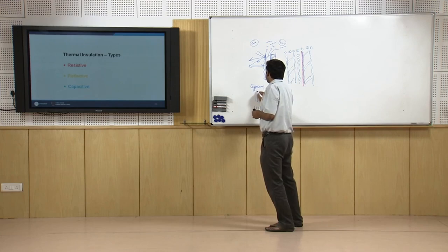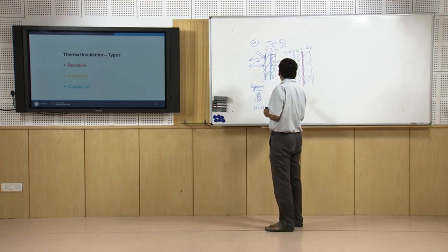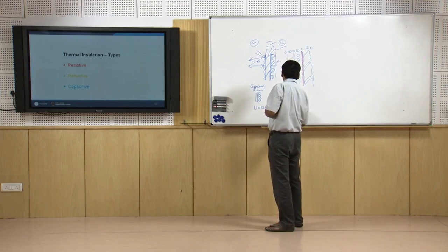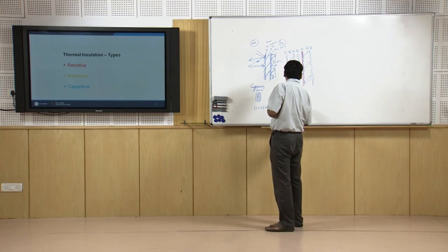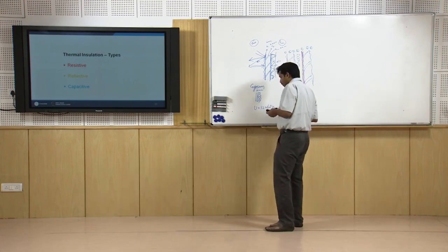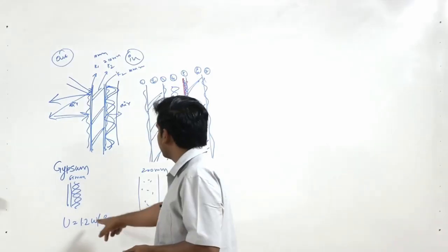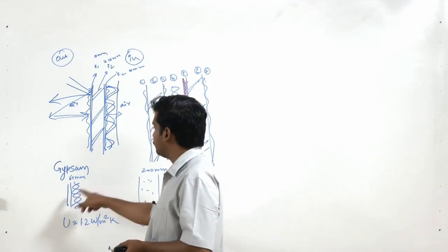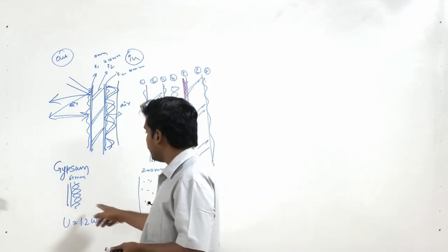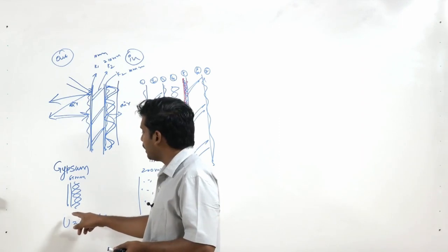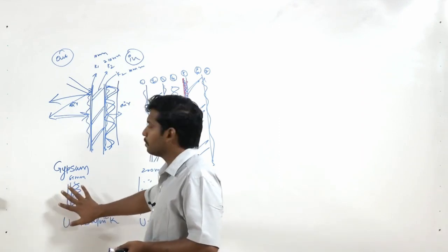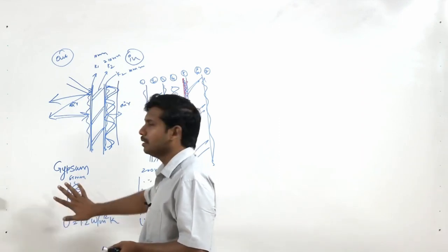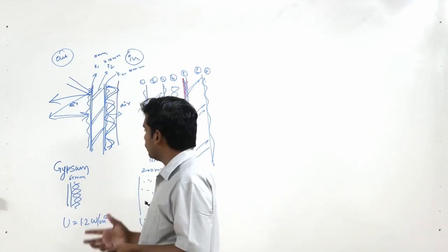This will be about 65 mm, the concrete wall is 200 mm, here the U value is 3.5 watts per meter square Kelvin. Now, this U value is more or less three times of the gypsum wall. Advantages, if you calculate conductive heat transfer, this is really advantageous. If it is air conditioned, if it is sealed, the whole thing works really in a good way.